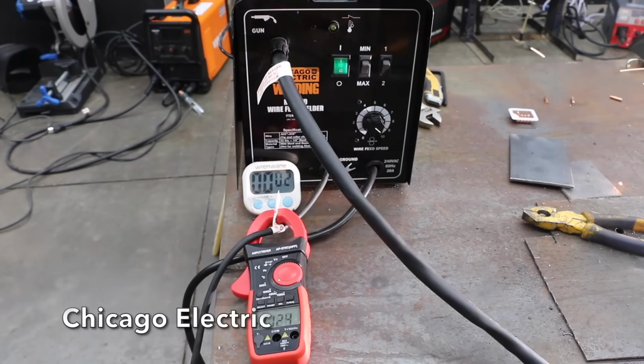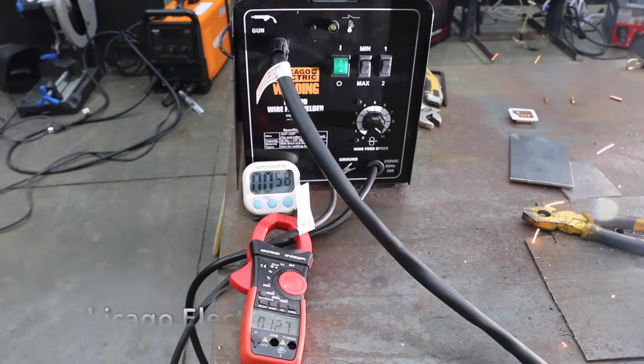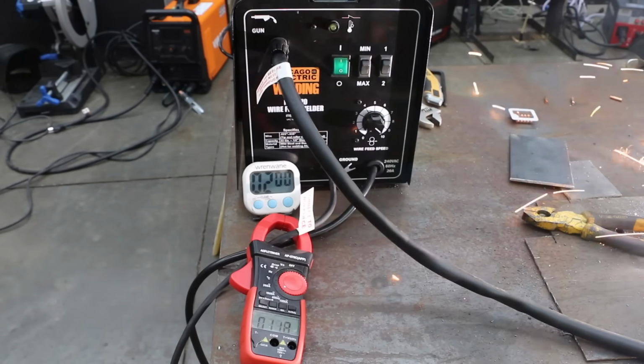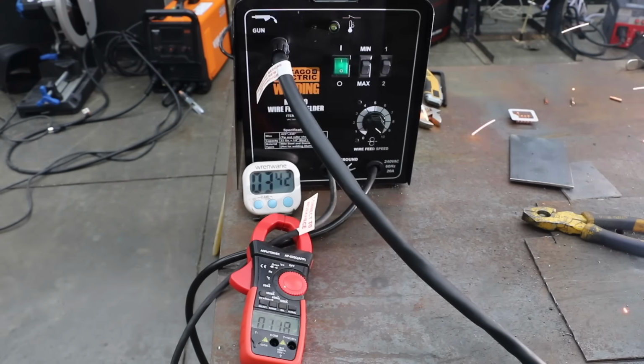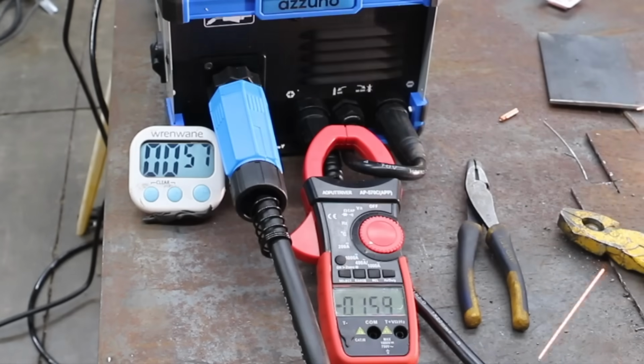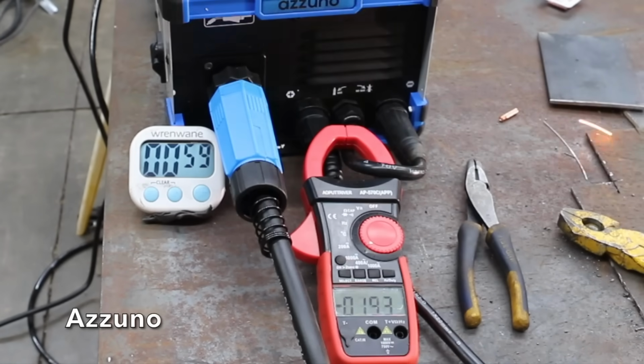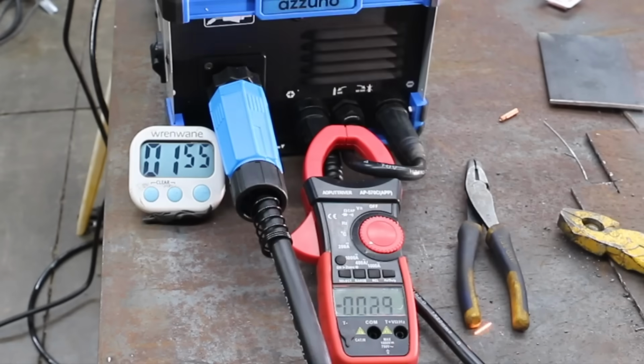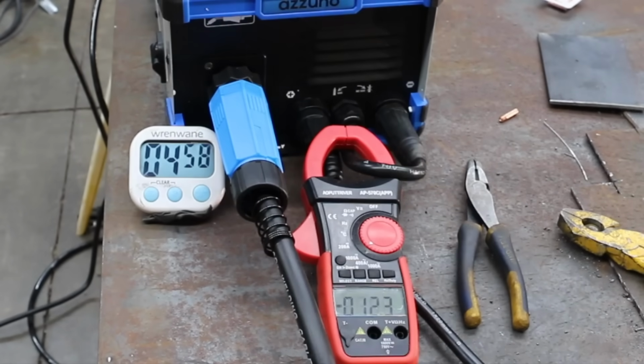After about a minute, the Chicago Electric was at 127 amps and dropped to around 100 amps after 2 minutes. And the Chicago Electric overheated and shut down at 3 minutes and 43 seconds. And the Azzuno is doing by far the best yet at close to 160 amps after a minute. And the Azzuno stayed very close to 123 amps during the rest of the 5-minute test.